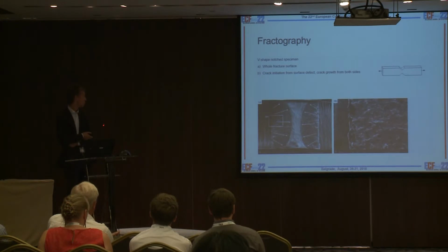This is the V-notched specimen. It has, of course, a stress concentration on both sides, so the crack will propagate from both sides. And we see that the crack is initiated from lack of fusion in the surface. And we can also see, I will show this also later, that there are some unfused particles in